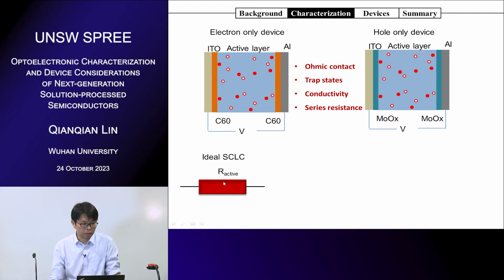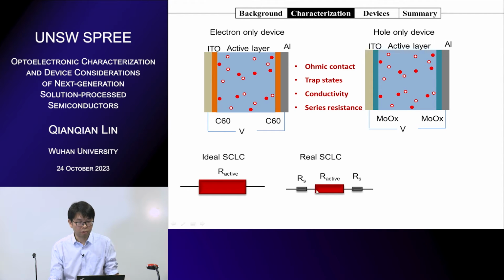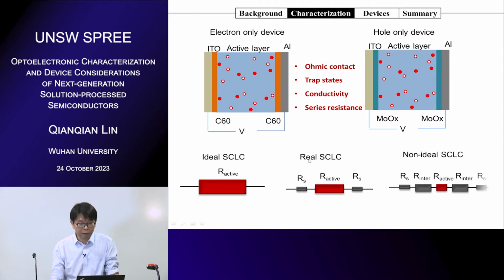For ideal measurements, we should measure the resistance of the whole device. We get the JV curves, and we can extract the mobility. But for real measurements, we always have series resistance, we have ohmic contact problems, and it can also be affected by the trap states. In this case it's also good because the resistance of the active layer is much larger than the contacts. So it's reliable.